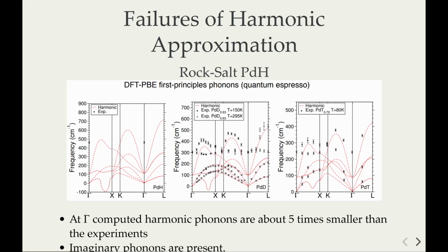So density functional theory predicts this system to be unstable. We know from experiment that this is not true—the system is stable.